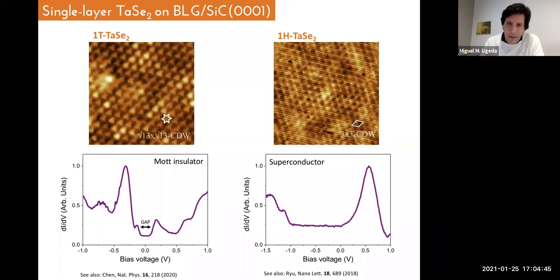In this system, it's very common to find two different phases. The 1T phase, which is a Mott insulator, this is the gap. This is something that Mike Crommie studied recently. And if you focus on the H phase, which is similar to that in niobium diselenide, you can see the 3x3 superlattice, the charge density wave, nothing changes. The electronic structure on the larger scale is quite similar.